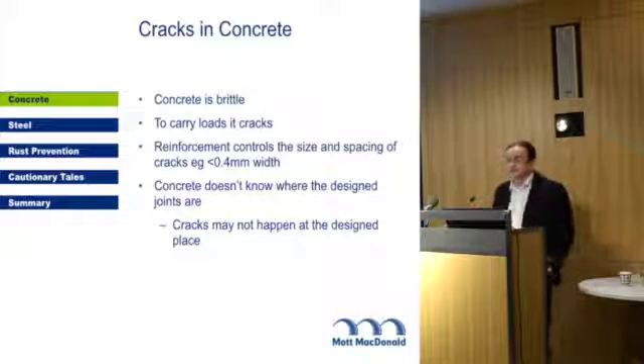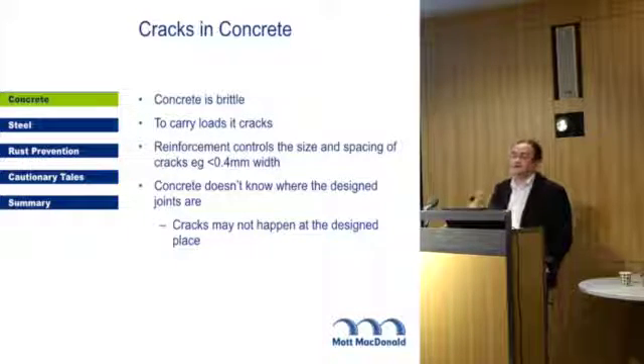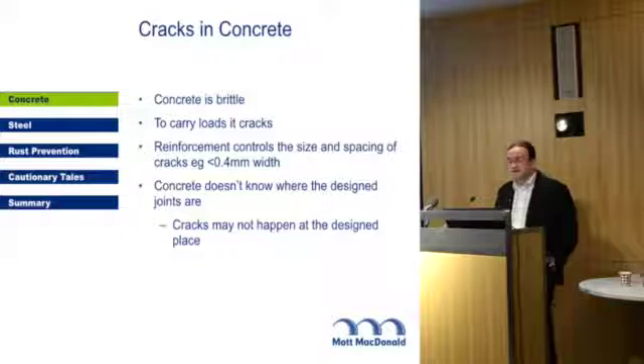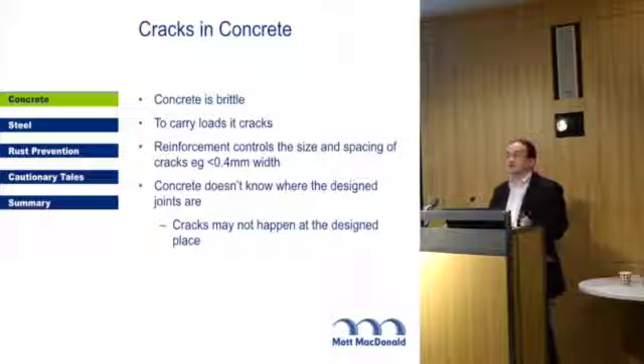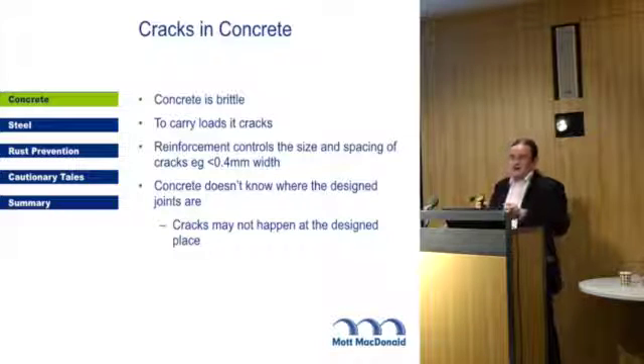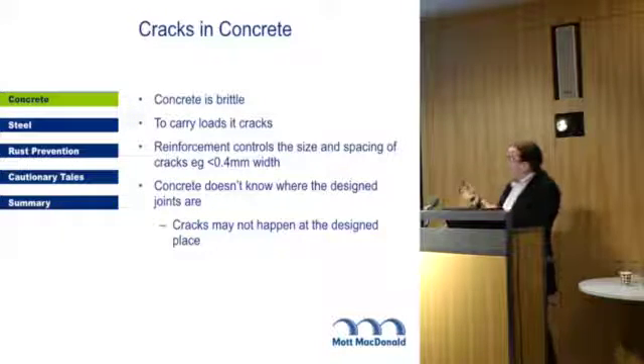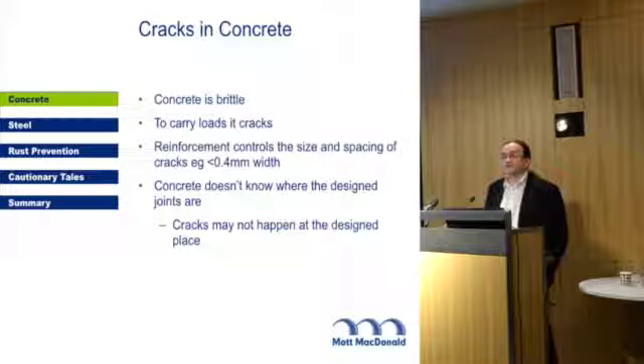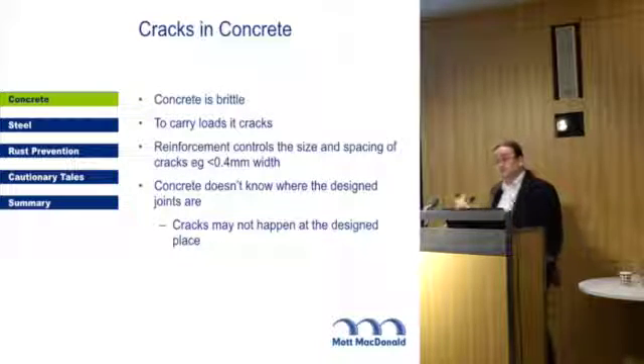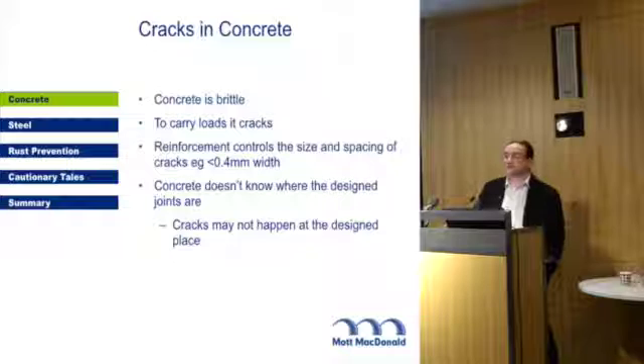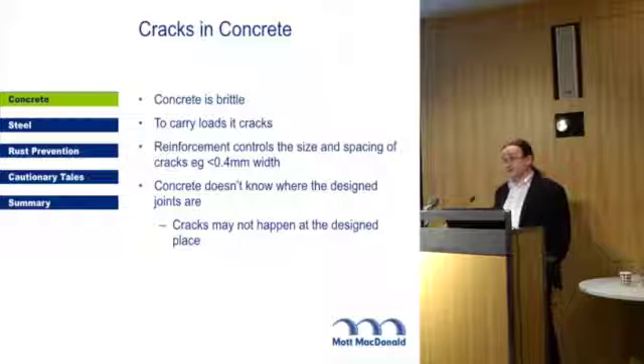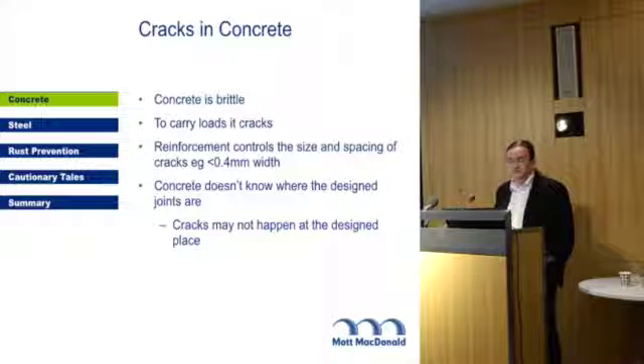Right, to carry the loads in concrete, it cracks. A lot of the early reinforcement designs we have are basically there to control the size and spacing of the cracks. That's kind of what they're there for. Typical design code used to be make the cracks less than 0.4 millimetres in width. Wonderful. If you want a water retaining structure, you make the crack less than 0.2 millimetres width. The Euro codes have changed all that, so there's a whole range of other things you have to consider, but that kind of worked for a very long time.